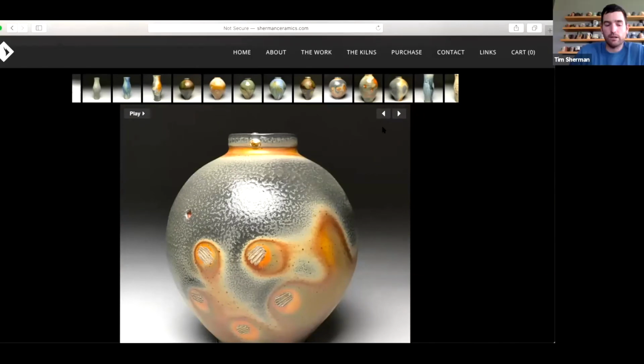Right. If you go too slow and you run out of time or fuel or resources, that's when you get that unmelted, those really stark differences in temperature between maybe the front and the bottom or the top and the back. There's always been a sweet spot for me, that if you stay in that zone, good things will happen. Your kiln will gain in temperature, but you're also going to get these carbon trapping, these dark halo type of things that happen from a slow moving flame.